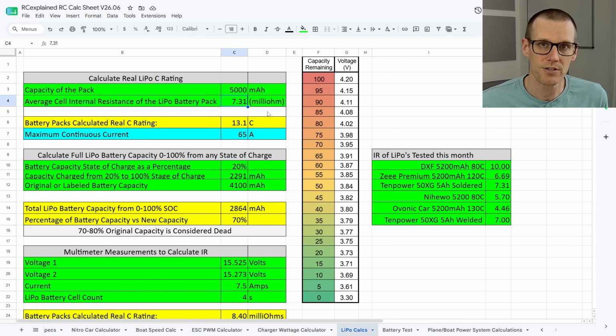When we go and change that internal resistance from 7.31 down to 7.00, we can see that we go from 65 amps to 67 amps. The difference between the 7.00 and the 7.31 is almost negligible when we're talking about that much difference between each one of those cells. So now that we know that our values here show us that we should be able to deliver somewhere around 65 amps continuous, this we know is not conservative at all. It's actually out the opposite side of the spectrum. We can guarantee that these cells are going to get really hot quite quickly, and that's exactly what they did.